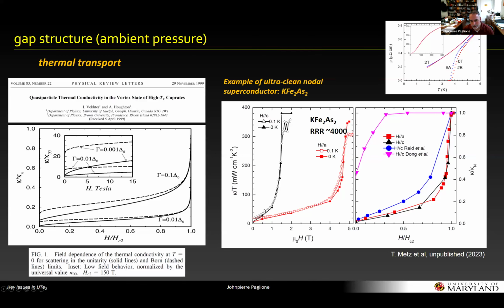And you can see here, now this is what's believed to be a D-wave superconductor, which has line nodes, so the zero field value is expected to be a bit different than a P-wave or point node superconductor, I should say. So it actually has a finite value, which is consistent with the line node superconductor. But you can see that the evolution with magnetic field is almost flat. So just to say that if you have an extremely clean superconducting system and you measure the thermal transport, it's not crazy to expect that this field evolution is very flat. And in fact, here it is. This is data we actually measured.